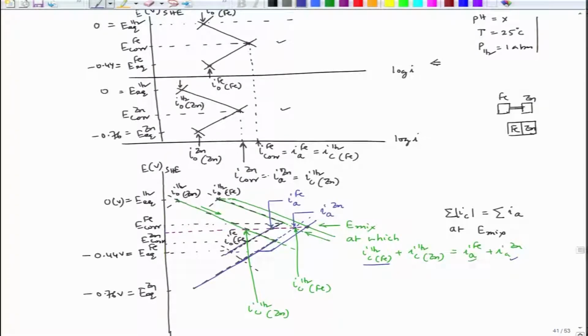Now, interestingly, we see that after coupling, iron dissolution rate has gone down from the no zinc coupled case. The corrosion rate of iron when it was individually exposed to the acid is higher than the corrosion rate of iron when it is galvanically coupled to zinc. That suggests that the corrosion rate of iron goes down. But what happens to the zinc corrosion? The zinc corrosion rate was at this point and has gone up to this point, so the zinc corrosion rate has increased.